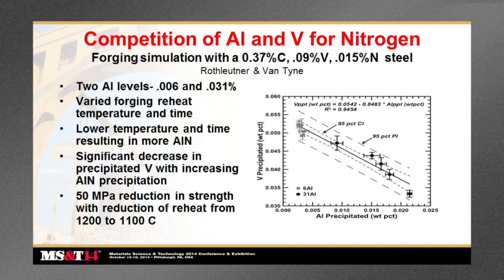What they found, as you can see on the graph on the right, is that as the amount of aluminum that precipitated increases, the amount of vanadium precipitate that occurred decreases. So in effect, it was clear evidence of aluminum stealing nitrogen away from the vanadium and reducing the amount of vanadium precipitation that occurred, therefore lessening the vanadium nitride precipitation strengthening. In fact, they measured up to a 50 megapascal reduction in strength simply by reducing the forging reheat temperature from 1200 to 1100 C.